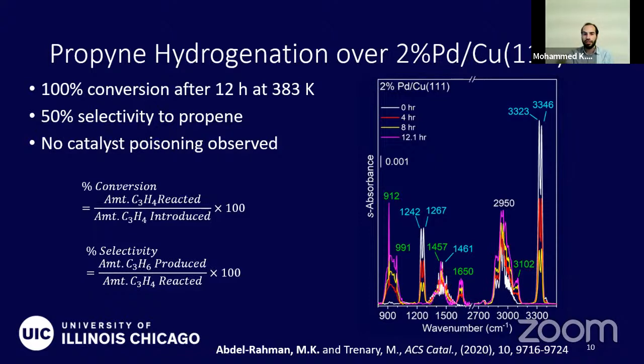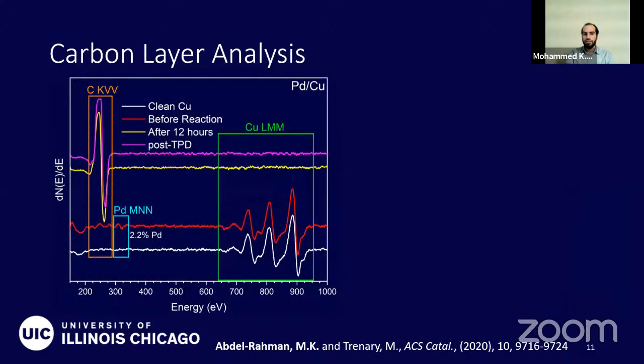So since we know half of the propyne goes to propene, the other half has to go to something else. And so we turn to our other techniques, such as Auger electron spectroscopy. Here we can see that our surface after the reaction, in the yellow and the pink spectra, is shown to be all pure carbon, as opposed to prior to the reaction, when we had palladium and copper surfaces.